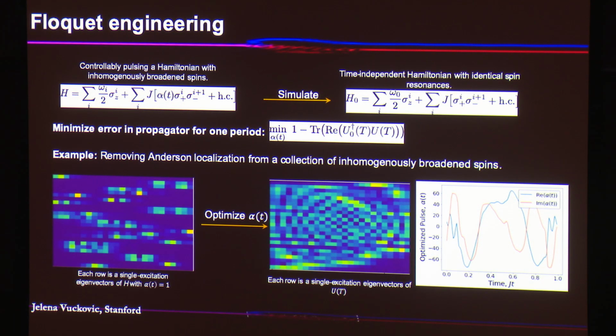So that's one component, engineer the structure. And the other component is, well, what about your emitters? Because they're not all the same. How are they going to talk to each other? And of course, you can tune each emitter separately, but that's never going to work, right? It's really hard, especially if you go to millions. You can't put electrodes on each of your emitters. So with Ignacio Cirac, we're working on actually doing something different. You start from the system that has some inhomogeneity, and then you optimize your driving in order to make them talk despite those inhomogeneities. And it turns out that that's possible.